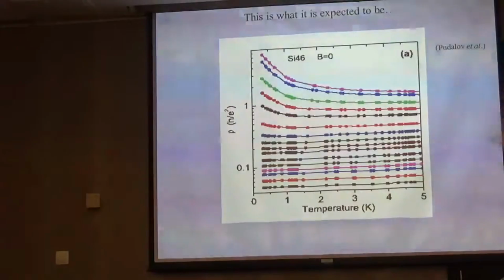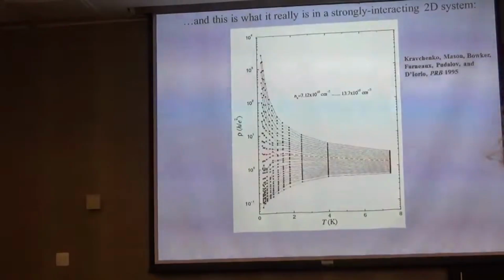But when the number of electrons goes down, disorder also increases because you don't screen so well. And you can see, as we go down in temperature, resistance increases exactly as it's supposed to according to the conventional theory. Here, you cannot actually see this increase on the scale I show. But if you look at the graph very carefully, you will see that it does increase. Okay? So that's a traditional poor quality sample. Now, what happens if you take a high quality sample? High quality means you have very few scatterings, very clean.